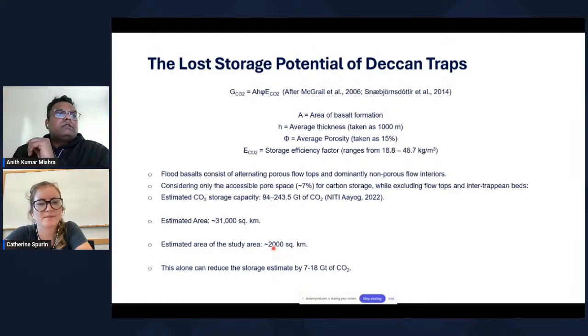if we subtract this 2,000 square kilometer area where we have complete mineralization of secondary minerals within the pores, using this equation, what we can estimate is that the theoretical storage estimation given by the government of India, which is 94 to 243 gigatons of CO2, can get reduced by 7 to 18 gigatons. So it will be around 87 to 225 gigatons of CO2. So an area of 2,000 square kilometers alone can have this much impact on the field scale CO2 storage estimation for the Deccan traps.